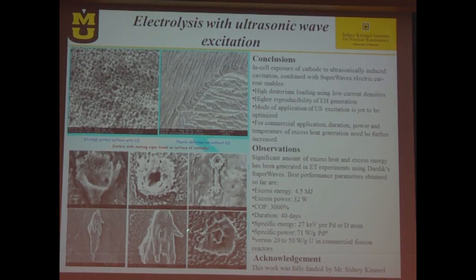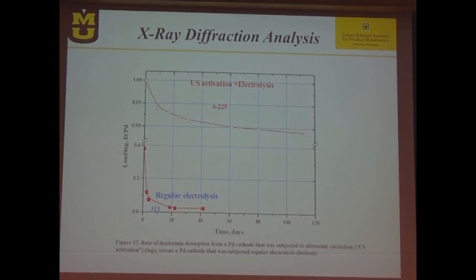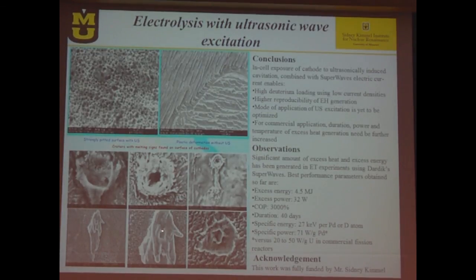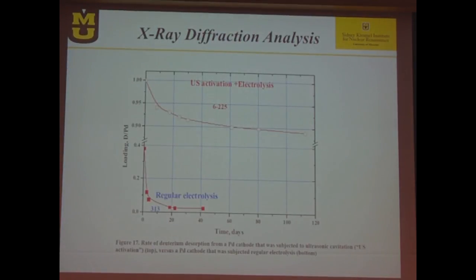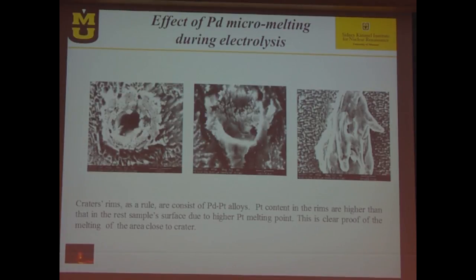Also, we see craters, all kinds of craters spread on the surface, and there is no doubt that melting took place. You can see it even visually, as you can see here. But as you will see shortly, we analyzed it with SEM and EDX, and we saw that here in the rims of the craters, there was an increase of concentration of platinum. Now, in any electrochemical cell in which you have palladium as cathode and platinum as anode, there will be ions of platinum precipitating on the cathode. So this is nothing special.